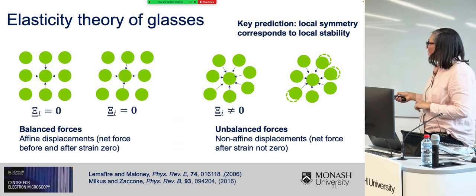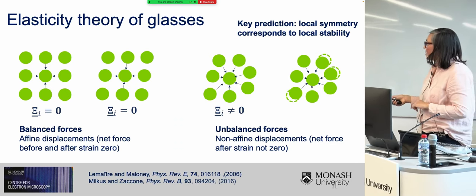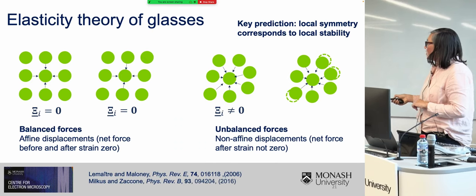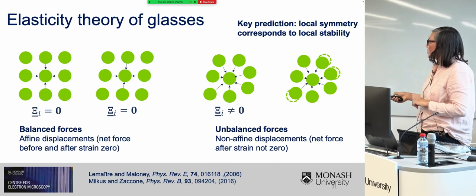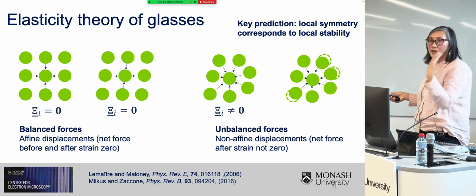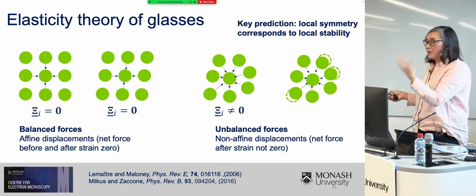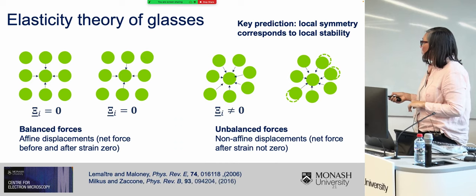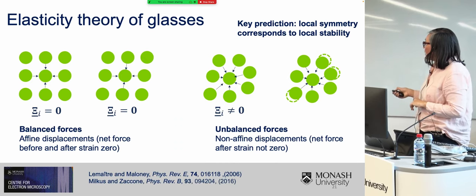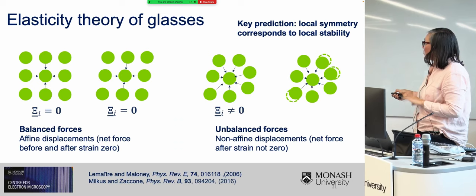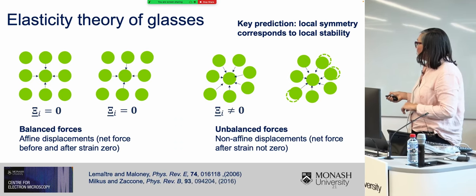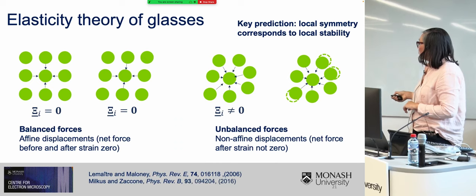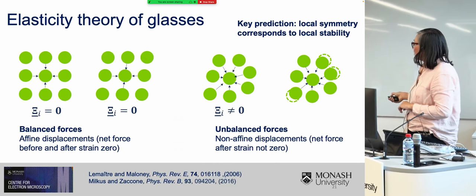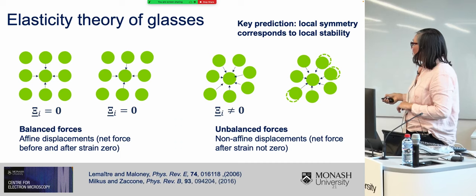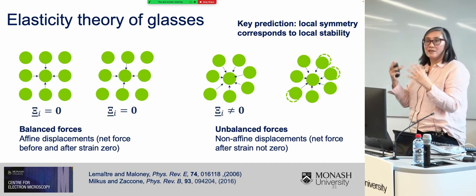So here you can see again, if we have a structure which is centrosymmetric and we strain it, then after the strain, the structure is still centrosymmetric and the force imbalance is zero. So it will just transform with the same magnitude and direction as the applied strain. If, however, we have a non-centrosymmetric local arrangement, then after the strain has been applied, the force imbalance will mean that the net force is not zero, and we will have some non-affine displacements after the strain.